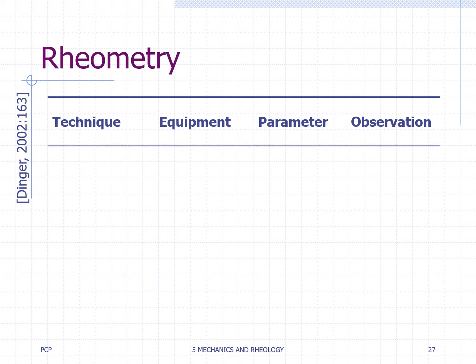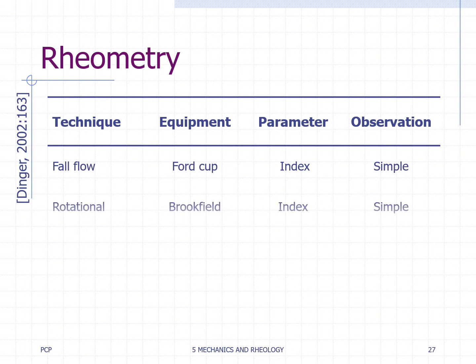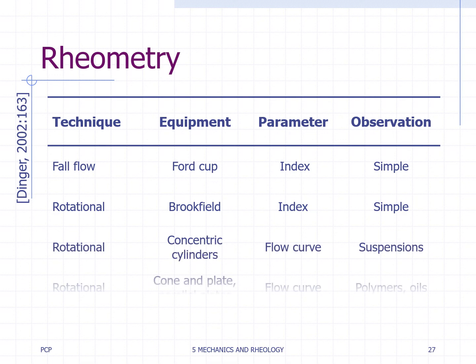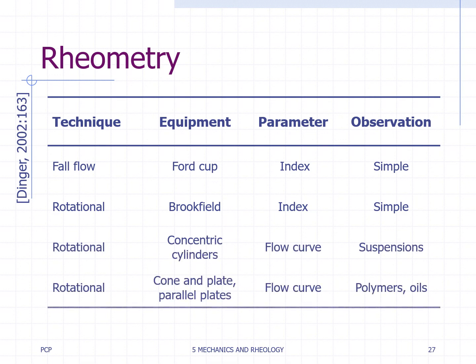Some common devices used for measuring viscosity in ceramic suspensions are summarized in this table. The Ford cup is a simple gravity device used to determine the timed flow of a known volume of liquid passing through an orifice located at the bottom. The least expensive commercial variant of the controlled rate rotational viscometer is commonly referred to as a Brookfield type. This device measures fluid viscosity at fixed rotation speeds by driving a measurement tool, or spindle, immersed in the test fluid through a calibrated torsion spring.